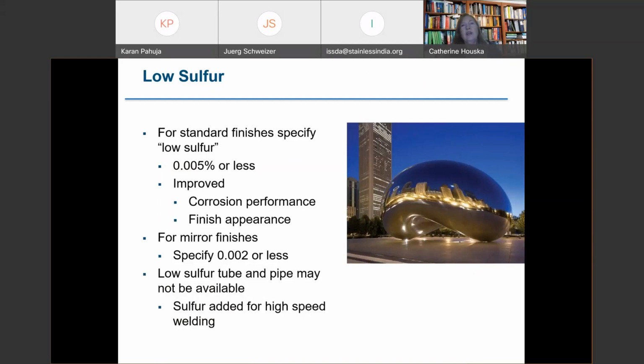So if the cloud gate had a high sulfur stainless steel, still within the specification, but higher in sulfur, everywhere where there was a sulfide on the surface, you would have seen a little tiny pinprick. And it wouldn't have looked nearly as attractive as it does because of those sulfides. Those sulfides also can, if you have a higher sulfur stainless steel, be places where corrosion can initiate. So there's more than one reason to consider a lower sulfur stainless steel.